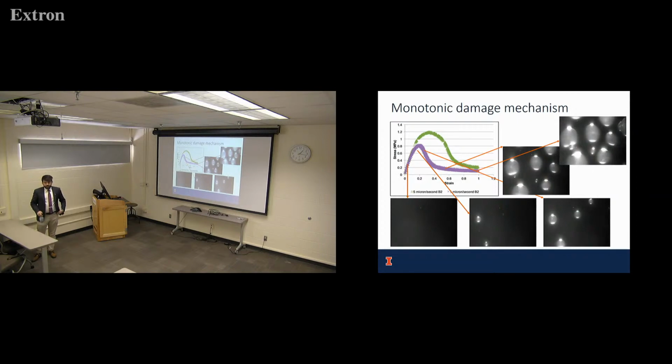Other question? Yeah, Javier. So from these pictures, you were saying that the brighter light is coming from the plate. Correct, yeah. So is this stress adhesion or cohesion or a mix of them? So this is cohesive failure, but what happens is it's such a thin film that once it starts to fail cohesively, there's just a very thin, tiny part of binder on the other side of the plate.